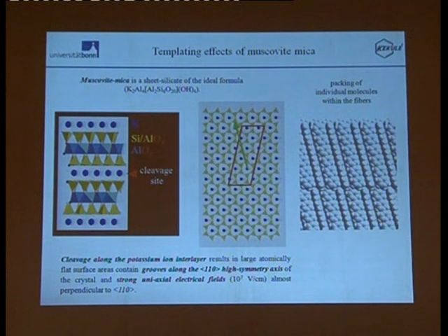So that was the point where the physicists came to us, we need new materials. If you look at this packing here, which is pretty important for the material property, because only in this way we have this nice conjugation of the pi systems, so this is very important for the properties. The only thing that you can think of is these para positions here, so these end positions here, because they do not interfere with the packing. If I would introduce any kind of group here or there, the packing would be gone, and the properties would be gone. We would have nice molecular properties, but we won't have material properties.